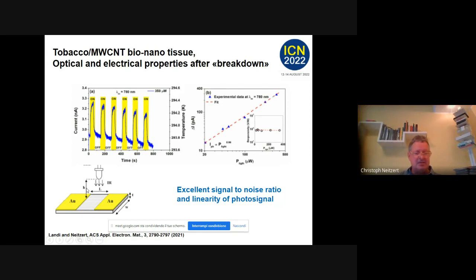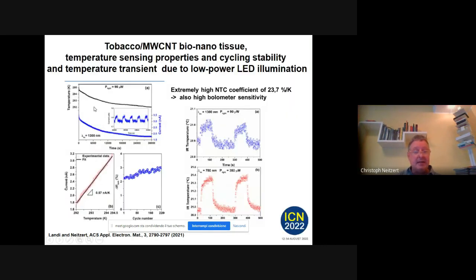Here it's just a simple, low-intensity LED. But even with this simple application we get a very high modulation, much higher than in the other cases. Here we do the same now overnight, where we measure the temperature and the current. You see the current is constant. If you zoom in, that is the dark current in the night.